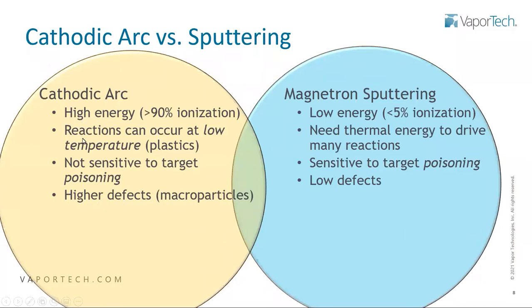That energy helps us drive reactions at low temperatures, which is really key for a lot of the applications we work in, where we're trying to apply our coatings onto plastics or other temperature sensitive materials. Whereas in magnetron sputtering, sometimes to drive the same reactions, you have to use thermal energy. You have to heat parts up, which a lot of substrates can't accommodate.